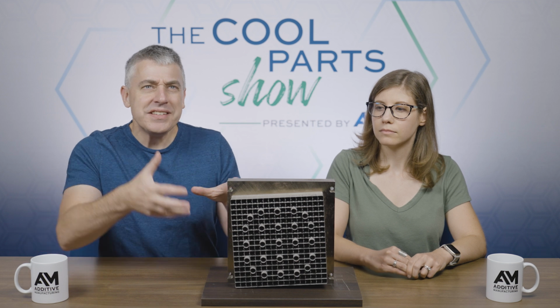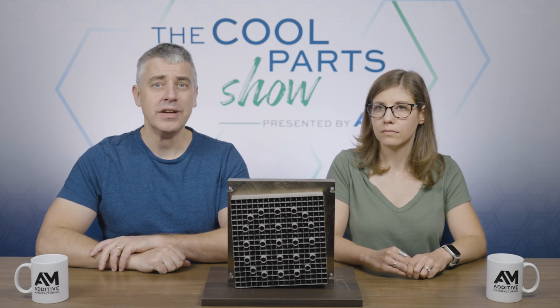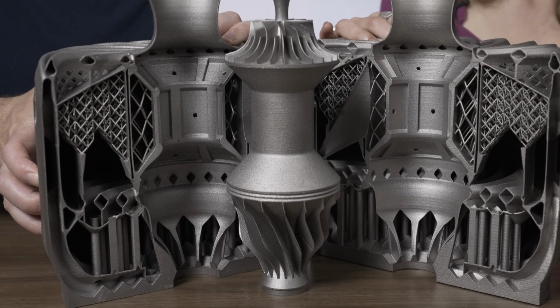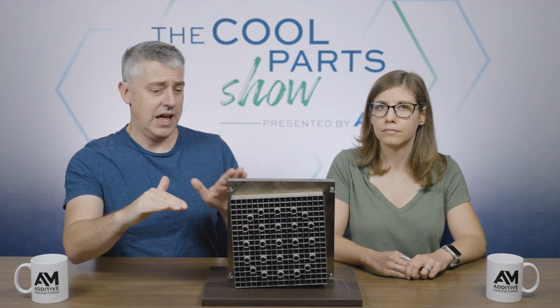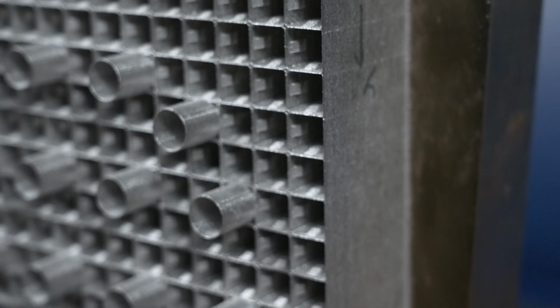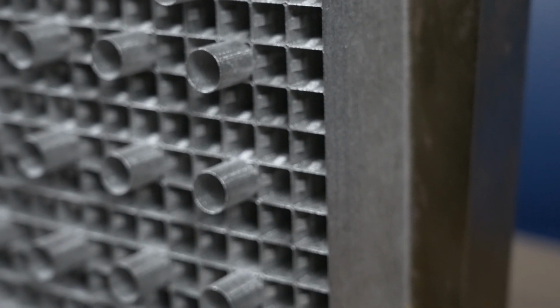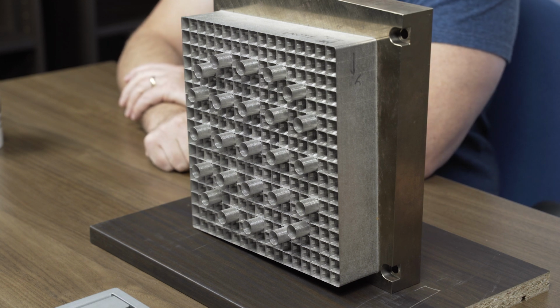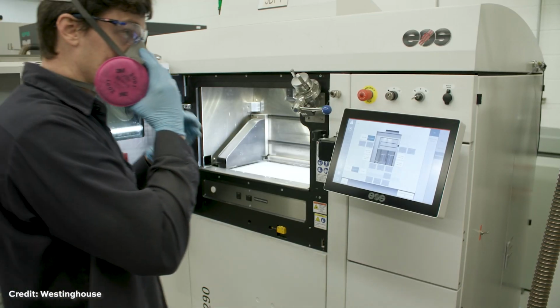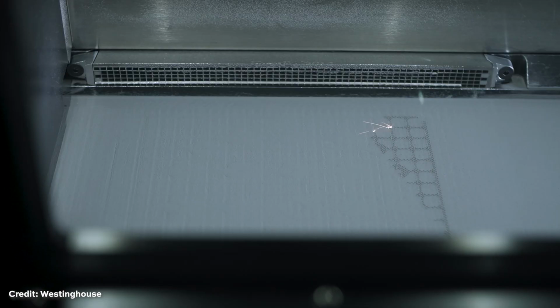But from a distance, this isn't necessarily an attractive part for additive. We often associate additive manufacturing with geometric forms that are very organically complex and intricate. This is a complex form, but there is a lot of squareness here, a lot of right angles and orthogonality, and these thin, straight walls. We were actually really glad that we ended up getting this part still on the build plate, because that makes it clear this was successfully produced all in one piece, in one build, through additive manufacturing, through laser powder bed fusion. We haven't mentioned the material yet this is made out of. It is Inconel 718, nickel-based alloy. It was produced on an EOS M290 machine, and it was made by the team at Carnegie Mellon University.